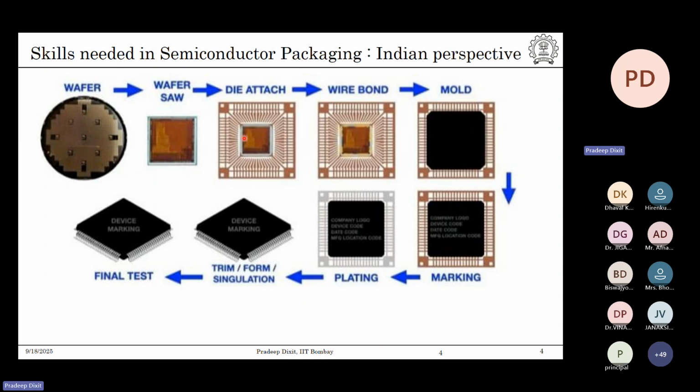Afterwards, as you can see, this is a lead frame, which is a metal frame. We need to provide electrical interconnection between the silicon die and the lead frame. It is not very clear in this picture, but on the periphery we have some yellow parts. Each of these lead frames is attached by a very tiny wire. These wires are basically gold wire, real gold. By making the proper connection between the silicon die and the lead frame, we provide an electrical interconnection. That means whatever the response of this silicon die is, that response is going to be transferred to this part. So that is wire bonding.